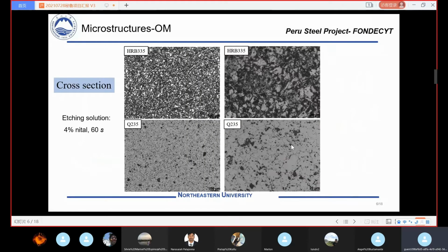Then this is the optical microstructures of the cross section. The etching solution is 4% nital, and we soaked these samples in the 4% nital for 60 seconds. In both microstructures we can find the white and the dark parts. The white part is the ferrite, which is detected in the XRD pattern, and the dark part is the second phase. Because the second phase exhibits lower corrosion resistance, it's easy to etch. The right figures are the magnification of the left images.